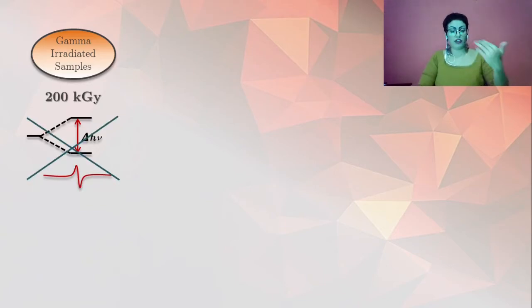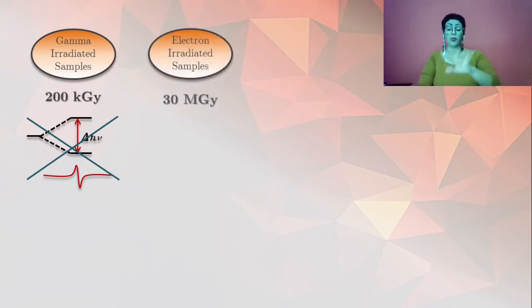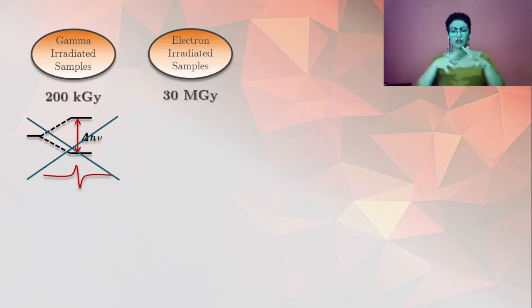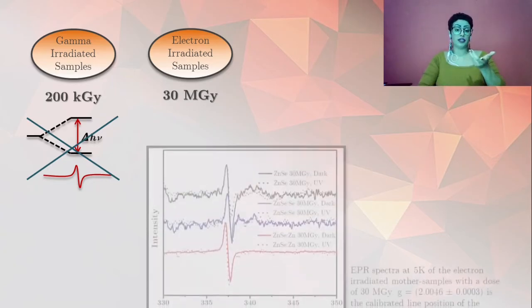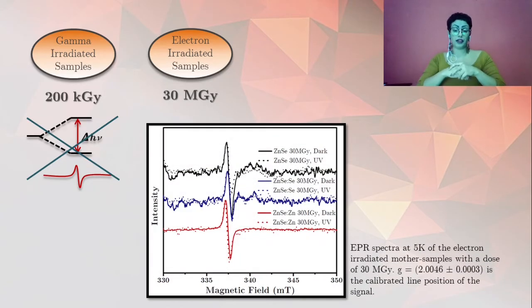Still trying to ionize some point defects, an electron-irradiated batch of samples was also prepared for each mother sample and submitted to particle irradiation with rapid electrons up to a dose of 30 megagray. The only EPR signal observed was an isotropic line close to the g-factor for the free electron, caused by a Zeeman interaction of a spin one-half without modification under UV laser excitation. The signal is too generic to conclude its origin.